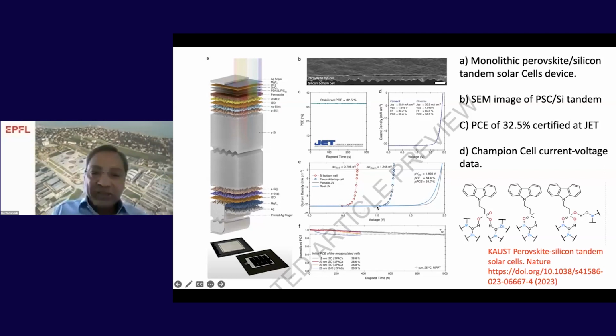Now, if you look at the blue line, this is the perovskite solar cell, which has 1.28 volts. And if you measure the silicon and perovskite tandem open circuit potential, it is 1.95 volts, which is just additive of the perovskite and the silicon solar cell. So this is a beautiful configuration to get the highest VOC possible using this type of self-assembled monolayers. So the highest efficiency, to my knowledge, is based on this optimization of the thicknesses of the various layers.